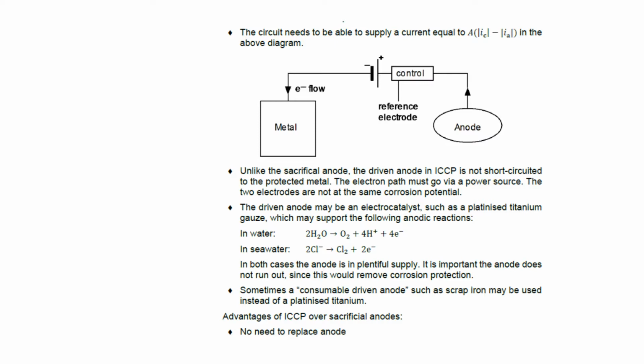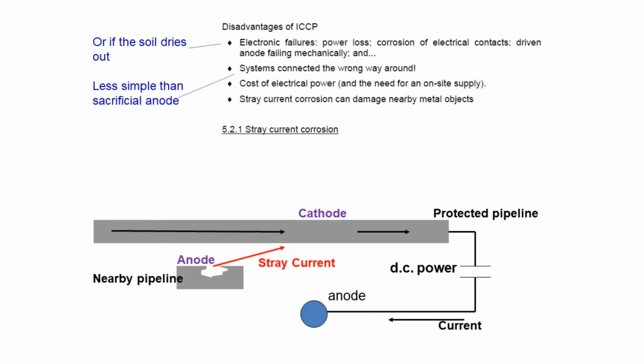Let's talk about advantages and disadvantages of the ICCP system. A big advantage compared to sacrificial anodes is we don't need to find them and replace them. If we have, say, a buried pipeline, that's a very big advantage, because accessing the actual pipeline itself to replace sacrificial anodes could be difficult. Whereas if we have a driven anode which is simply connected by wiring to the pipeline at a few fixed positions, and the wiring connections are not going to degrade, then it's going to be easier for us to get at the driven anode to service it if we need to.